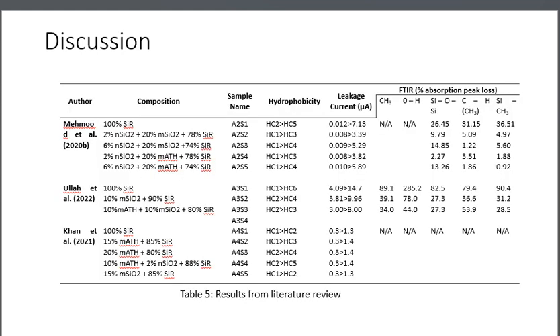Based on the literature reviewed, several key trends were identified. Hybrid coatings containing nano and microfillers containing SiO2 or silica and alumina trihydrate demonstrated improved performance compared to pure silicone rubber coatings. These improvements were observed across multiple performance indicators.